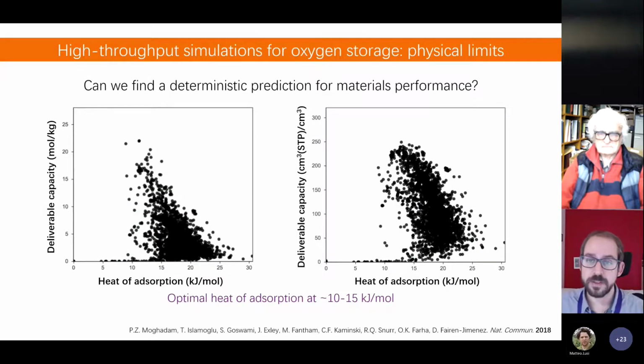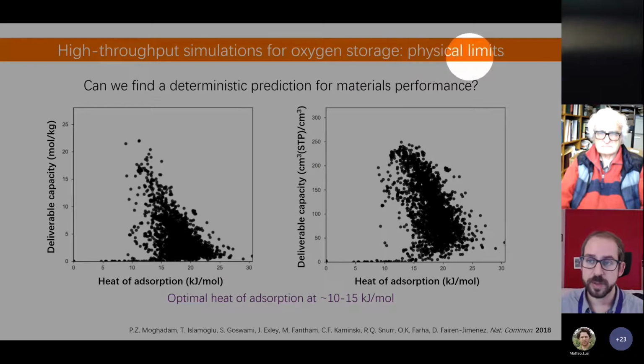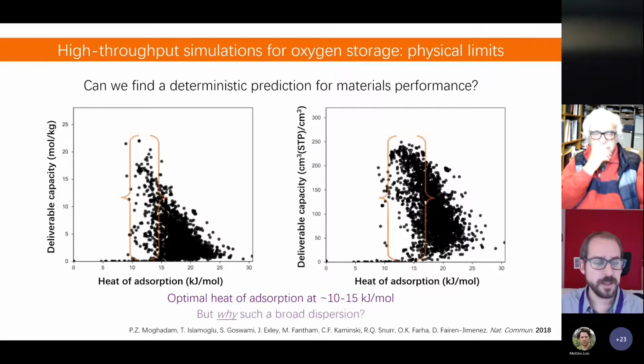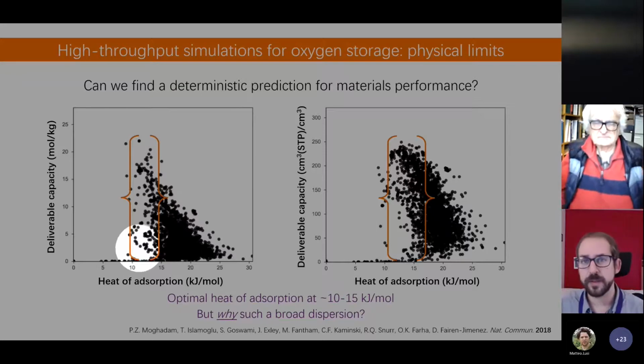This is for another application. This is for oxygen storage. Again, trying to explore what are the physical limits. If I have the gravimetric capacity and volumetric capacity as a function of the interaction of the oxygen with the metal-organic framework, I have 3,000 materials included in this slide. I can say the optimal interaction needs to be between 10 and 15 kilojoules per mole, but at the same time, I have materials that perform extremely well and materials that do not perform very well. So how can I really improve that?